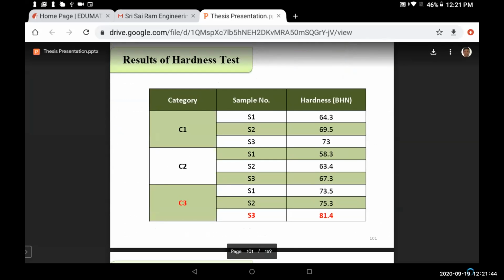But C3S3 has a very good hardness as compared to the other samples manufactured, that is 3 in C1, 3 in C2 and 3 in C3. So if you see, out of the 4 tests we performed earlier, C3 gives a very good performance. So again I come to say that the hybrid composite has its own impact, giving better mechanical property and behavior of the materials.